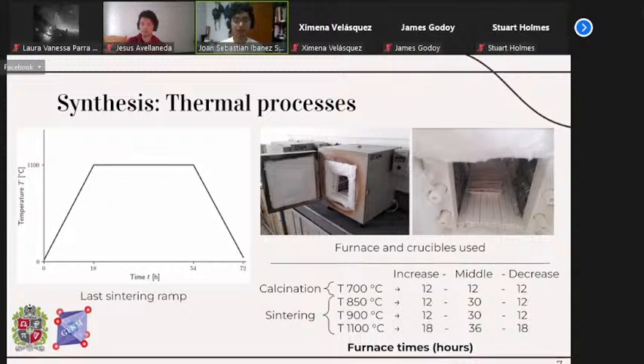We applied 3 different sintering ramps, and you can see the times that we used for each of the sintering ramps at the bottom right. Each of the ramps was of the same shape that we show on the left. We increased from room temperature up to a high temperature value. We kept that temperature for an interval of time, and then we let the material cool down again to room temperature.